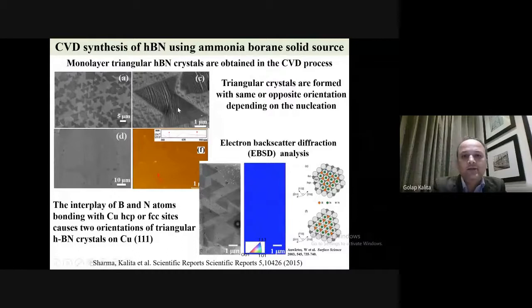So why does this type of thing happen? If you see from review papers, when you have nucleation of these crystals, if the growth of the crystal starts from a boron atom, you can have a nitrogen atom in the other case. So you can have this type of oppositely oriented triangular crystals of HBN. So it's a very interesting aspect of HBN growth by the CVD process.